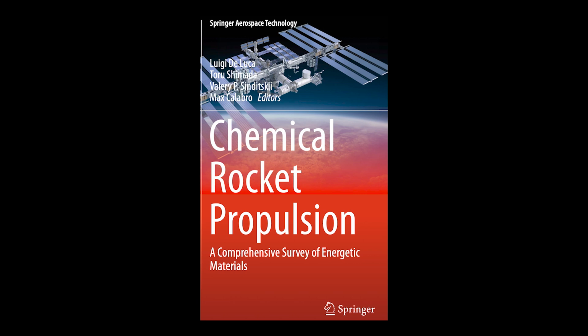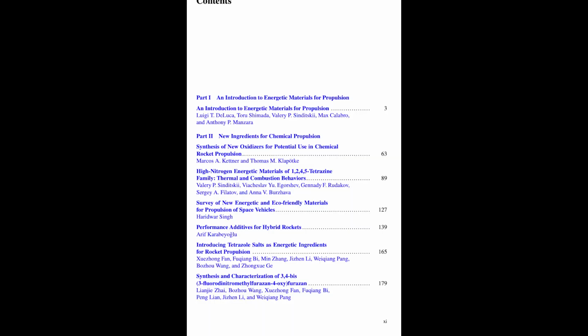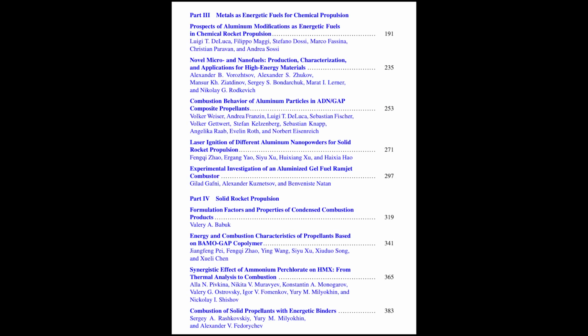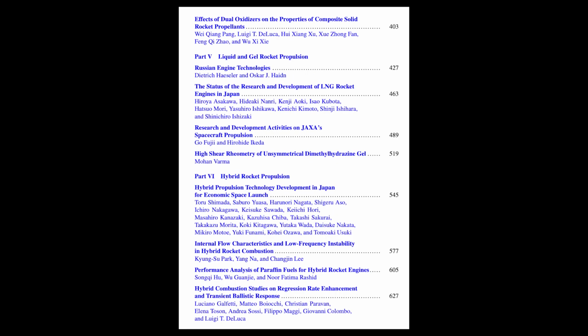Clever. And what did the tests show for propellants using both AP and ADN? The research confirmed that these AP-based dual oxidizer propellants could be successfully manufactured using standard vacuum casting techniques and that they burn steadily. Any differences in burning? Most formulations showed pretty similar burning rate responses to pressure. However, the specific combination of AP and ADN resulted in a noticeably higher burning rate and increased sensitivity to pressure changes. And particle size mattered. Yes, interestingly, for the AP-ADN propellants, using larger particles of ADN actually led to an increase in the pressure exponent, meaning the burning rate became even more sensitive to pressure changes.